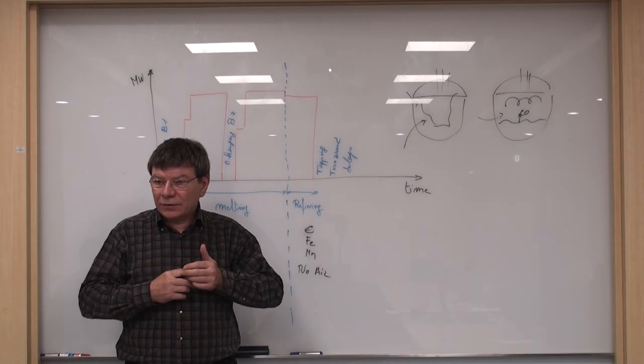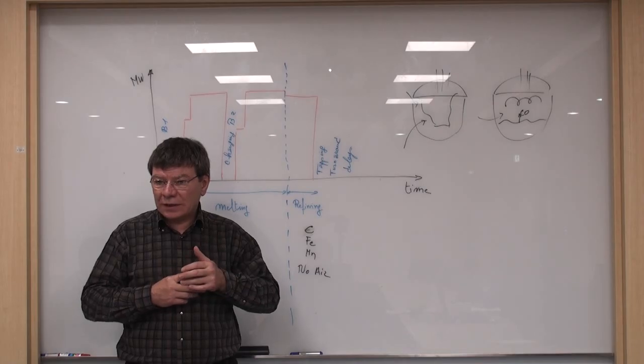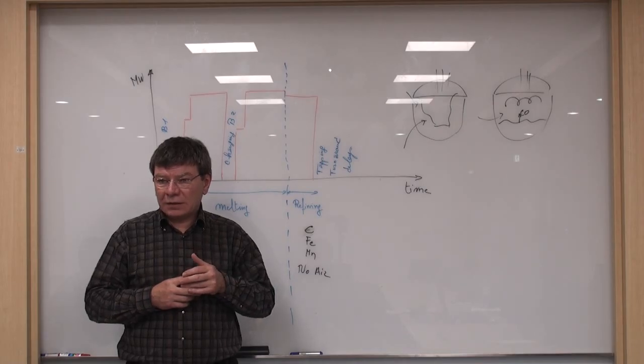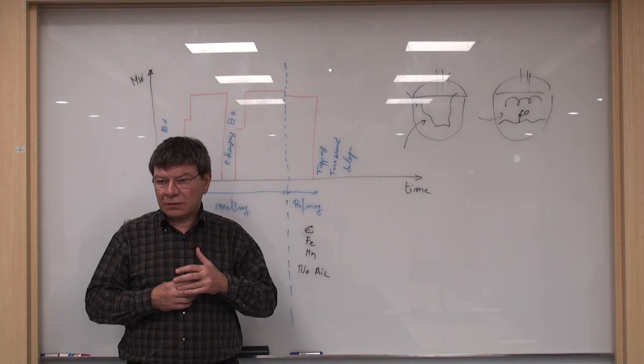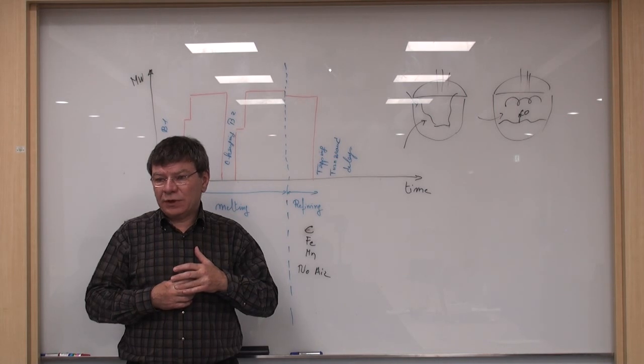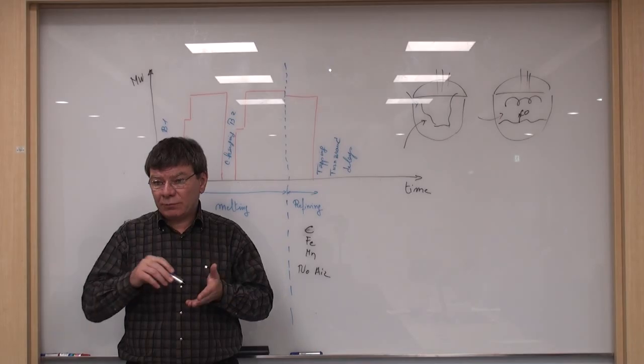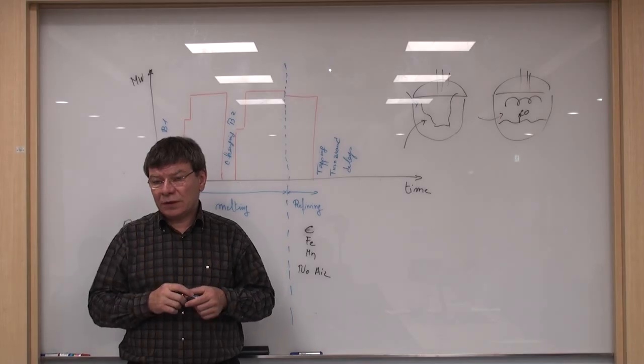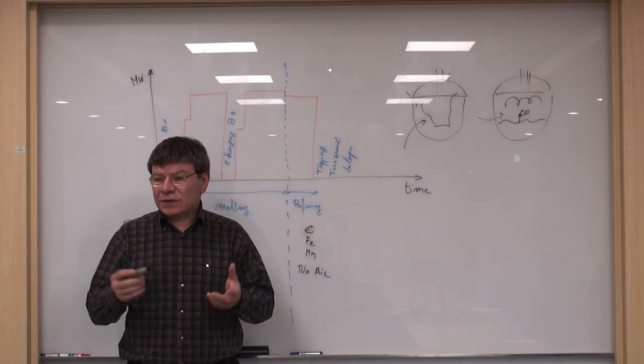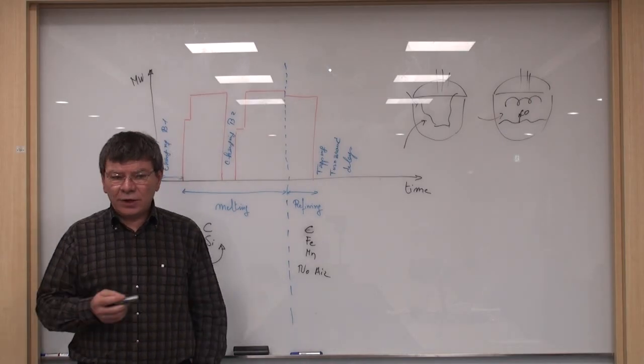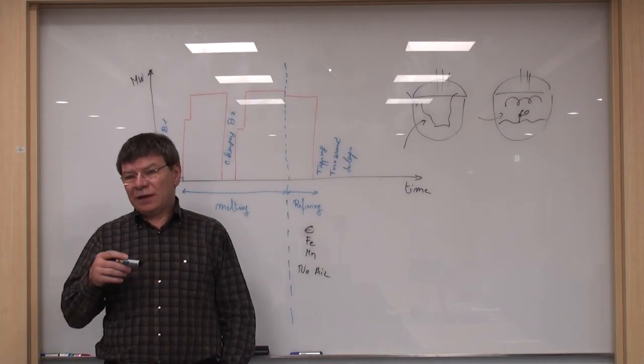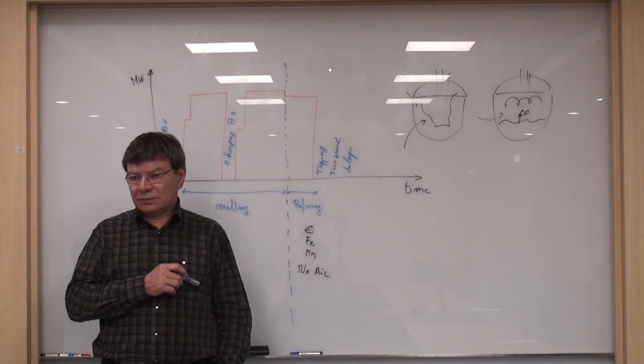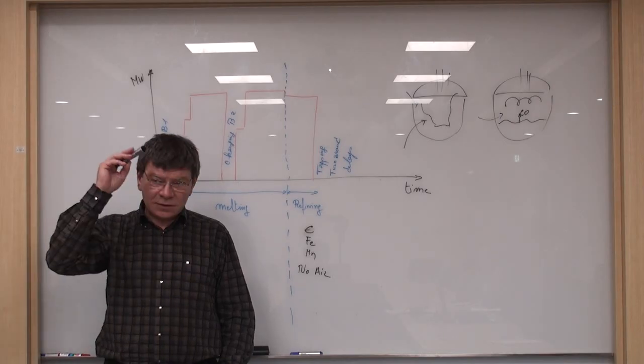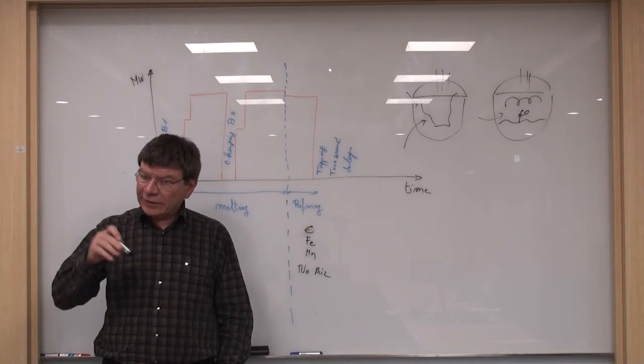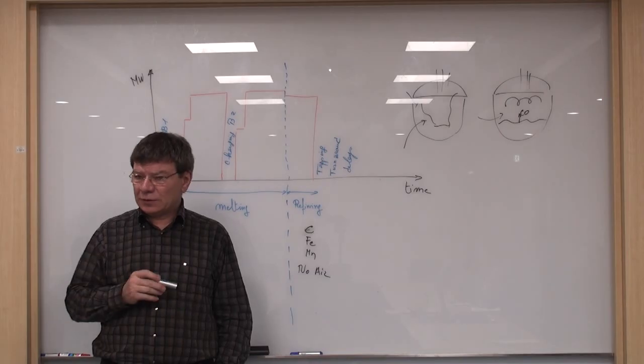Sure too. You increase the chromium oxide in the slag. And that's it. Especially during the flat bath. Because you increase the contact between the steel and the atmosphere. This is not useful, because there is no way to avoid having air in the furnace atmosphere. Otherwise it takes measures to tighten the furnace so much that you cannot work anymore.